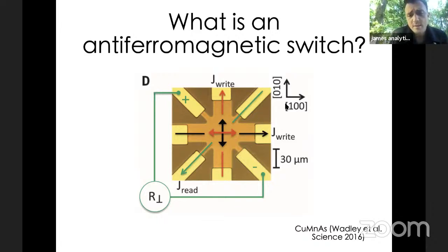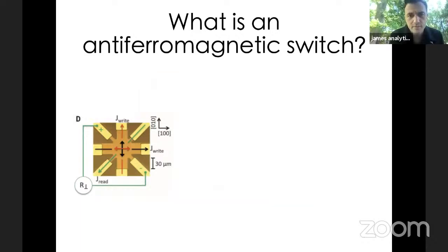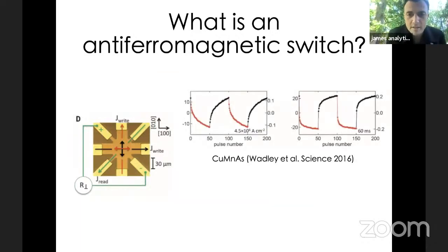But in this particular experiment, what you're looking at here is that you can apply current in two orthogonal directions, the black direction and the red direction. And what's happening is that the Néel vector is in principle being rotated in the central region between one orientation and the other orientation. And you can detect this using a read current at 45 degrees, where you can essentially measure the resistance changes in the central region. And whether it goes to a high resistance state or a low resistance state tells you whether you've rotated the Néel vector one direction or another. Okay, hopefully I didn't get too much of that incorrect.